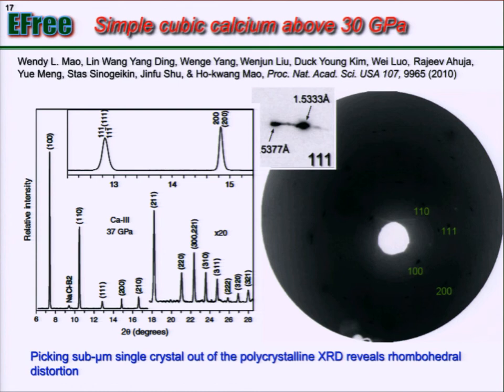And so the first thing we do is to understand what the crystal structure is. Calcium also has a very strange series of transitions. Usually at high pressure, you expect a material to go toward closer packing. So if you have BCC, body centered cubic, and you transform to FCC or HCP, that's closer packing. But this is completely reversed. You start with FCC, at high pressure it becomes BCC, and at even higher pressure it becomes simple cubic. Simple cubic has 6 coordination, BCC has 8, and FCC has 12. So it is completely reversed. And simple cubic, you can imagine, is like stacking a ball on top of a ball. It's really unstable normally. So there were a lot of theoretical calculations, and no one could figure out why it's simple cubic. But the diffraction looks just like simple cubic.